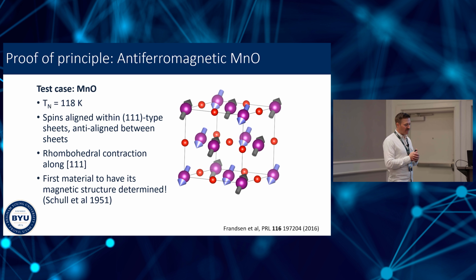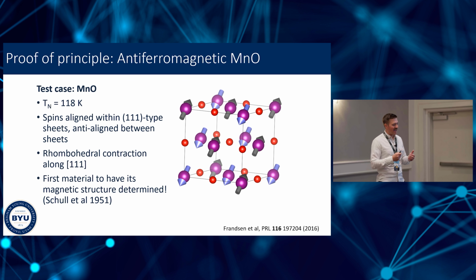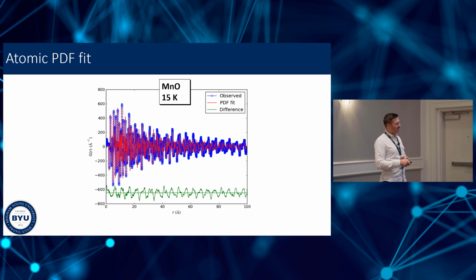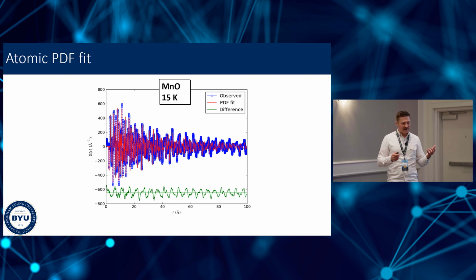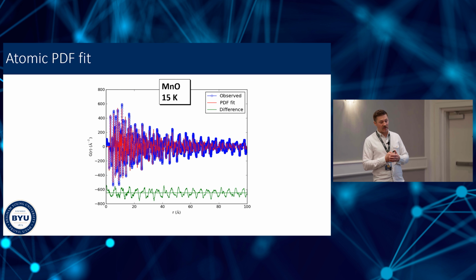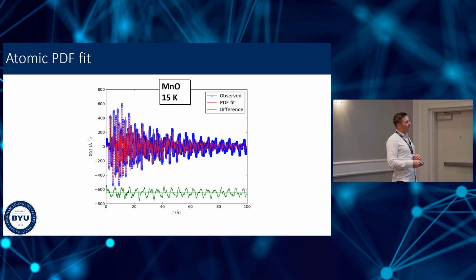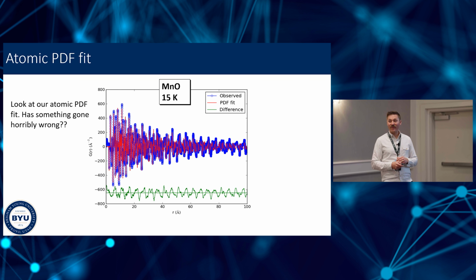So my first ever neutron PDF experiment was done on manganese oxide at Los Alamos at the NPDF instrument, which unfortunately is no longer available to the community. And this is the data we got. So here's the PDF data, and what I've done here is just a simple fit using the atomic structure of manganese oxide, the well-known rock salt structure. And this is the fit residual. And it looks like something has gone horribly wrong.